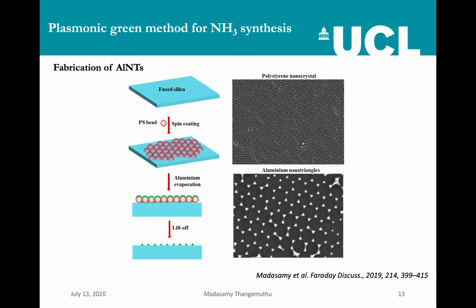And you probably ask, how large is your sample? In my case, I prepared 2.5 centimeters square. With this type of method, we can also prepare larger substrates, like 10 centimeters square. So with this aluminum, you probably ask what you are going to do or how you are going to break the nitrogen molecule. I did not use aluminum alone. I combined it with titanium dioxide semiconductor.